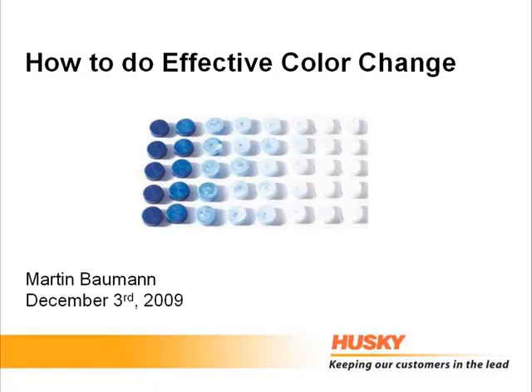There's a question in regards to what about if we run already at elevated temperatures and we're already seeing black specks, and then we want to do color change and increase the temperature even further? What would we recommend? In this case, I probably wouldn't recommend it. Now, black specks can come from different sources. So one of the things you may want to investigate first is why you have black specks in the first place. Black specks can be created through hang-up spots in the system. They don't have to be there. I would recommend not living with black specks, but rather trying to figure out where they come from. But let's say that's the process that you run today, and you elevate temperatures further.